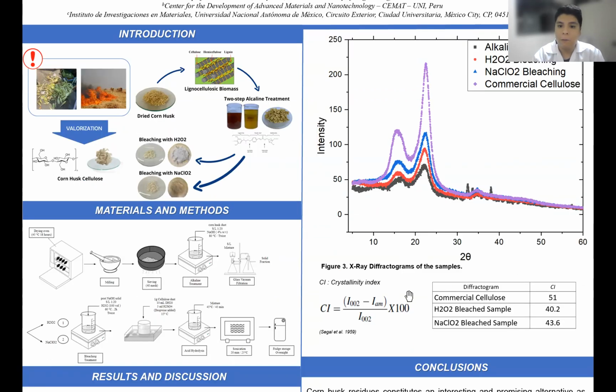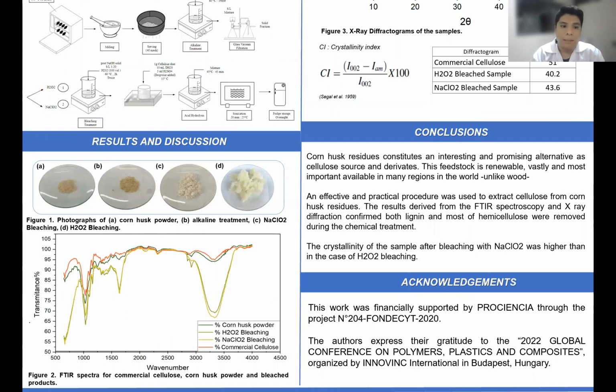Now, I would like to point out some conclusions. This work allows us to conclude that corn husk residues constitute an interesting and promising alternative as a source of cellulose and derivatives. This feedstock is renewable, vastly and most importantly, available in many regions, unlike wood. An effective and practical procedure was used to extract cellulose from corn husk. The results derived from the FTIR spectroscopy and X-ray diffraction confirmed both lignin and hemicellulose were removed during the chemical treatment.